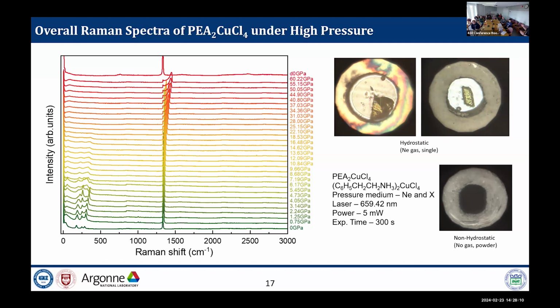The reason is that this PEA2CuCl4 sample is so sensitive and so easy to burn, so we can't use higher laser power. So we can see other peaks, but under 400 inverse centimeters there is a lot of change in the lattice mode. We can see some phase transitions near 8 gigapascal and 15 gigapascal. There are disappearing and arising peaks.